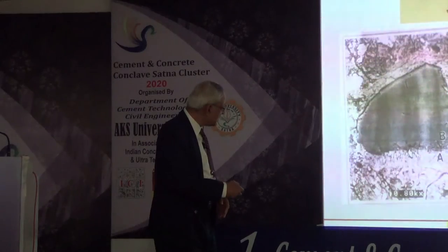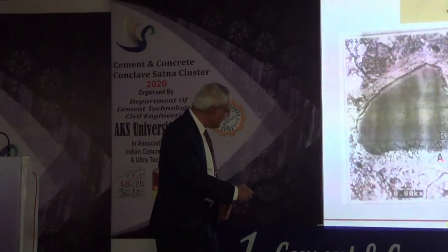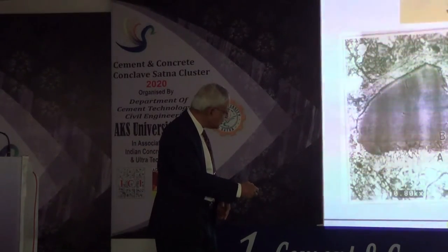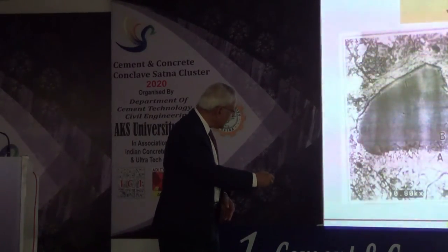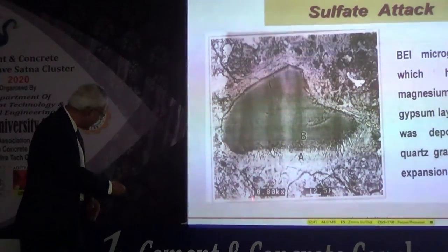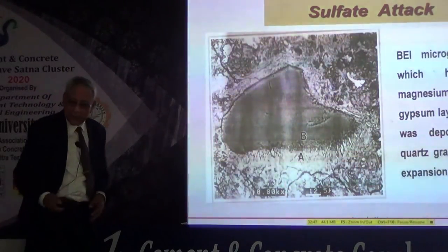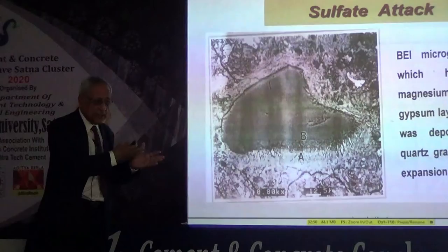But basically, this is an aggregate sample, a quartz aggregate. And you can see that because of the sulfate attack, all these needles you are able to see are gypsum needles. And this entire aggregate has been encircled by a layer of gypsum. And this gypsum exerts pressure and ultimately your concrete cracks. You can see the crack here, here, and here. So in other words, the sulfate reaction products lead ultimately to the cracking of the concrete.